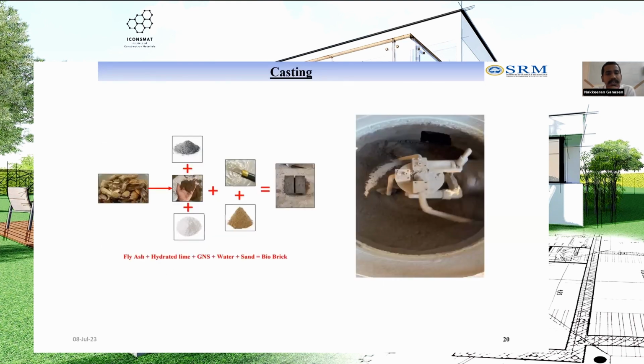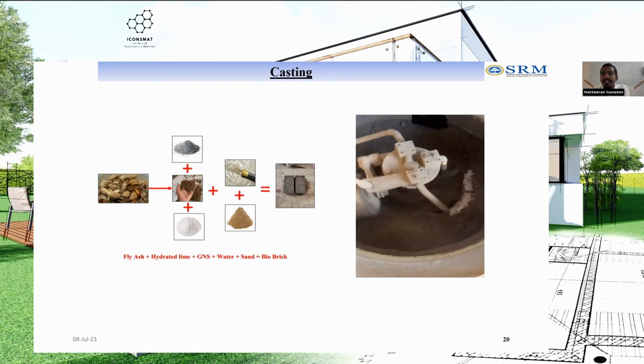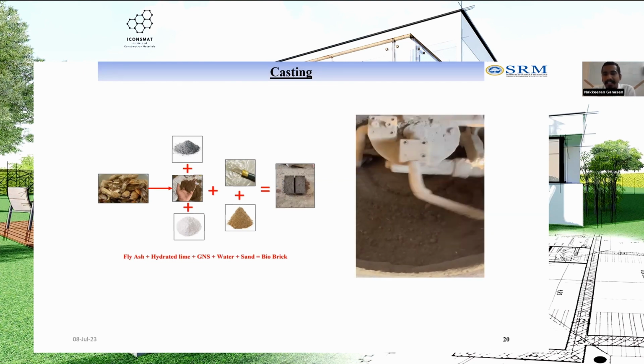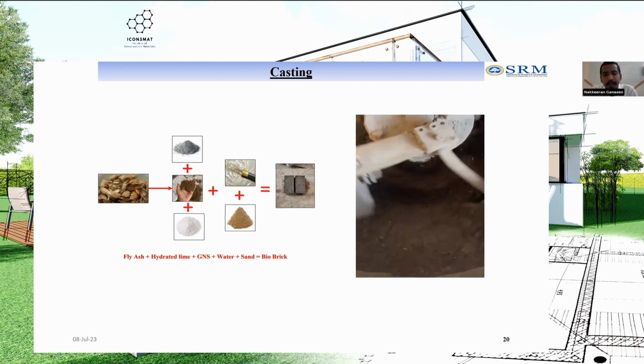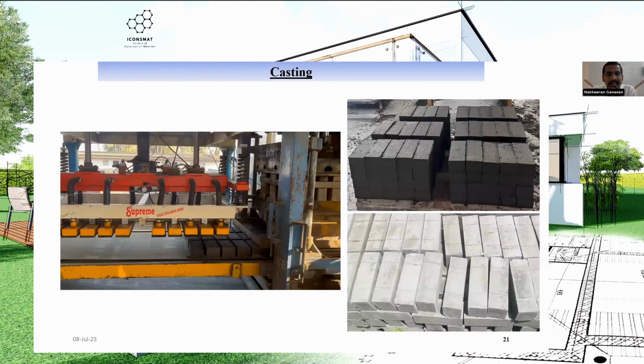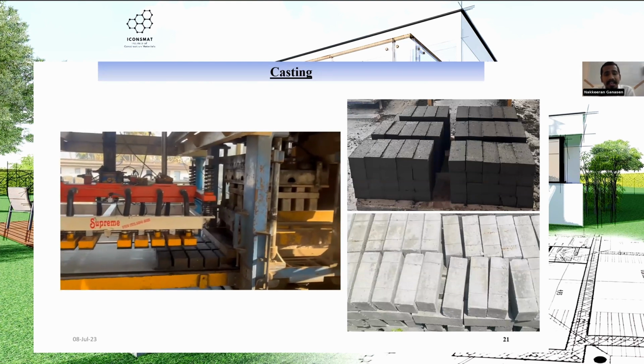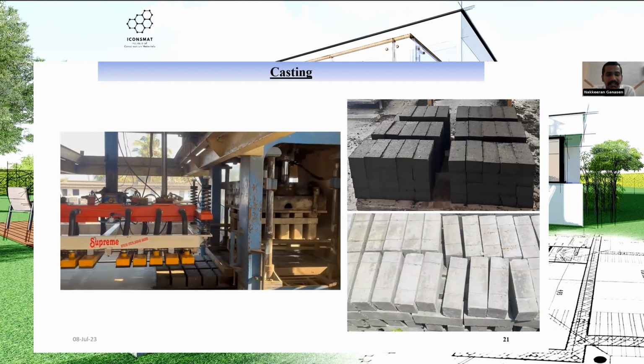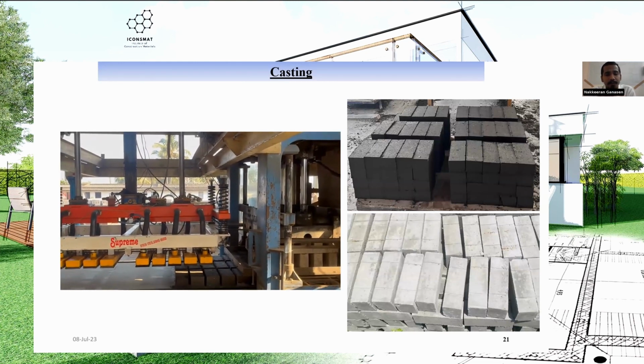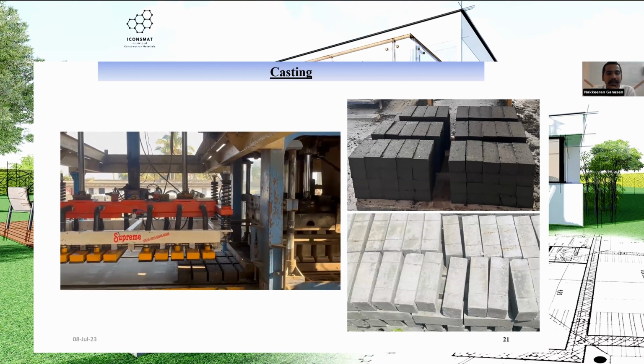These are the mix combinations we prefer. While using this GNS material, it is a little bit porous, so we plan to grind it properly and mix it in these machines. We properly grind and mix these 4 materials: the fly ash, hydrated lime, and the GNS. By grinding, we reduce the excessive pores in this brick. After that, we put it in the compression machine. It is filled with materials, and we compress the bricks. When you compress the bricks, it comes out perfectly as a product.